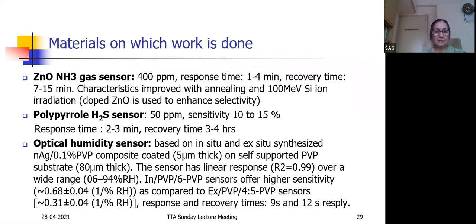And when measured with Ex-PVP, it gives a sensitivity of 0.31 per percent. The response and recovery time were 9 seconds and 12 seconds respectively. This was quite good, and it shows good sensitivity compared to the commercially available sensors also.